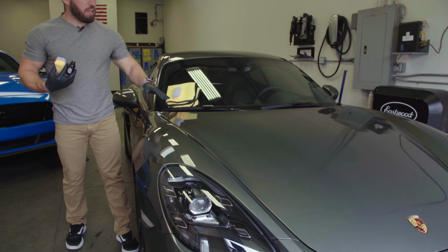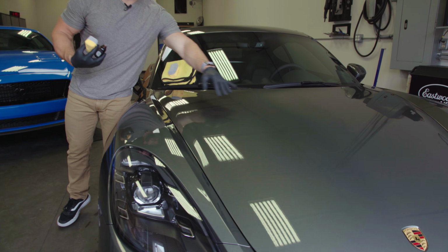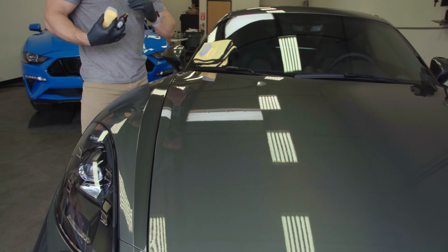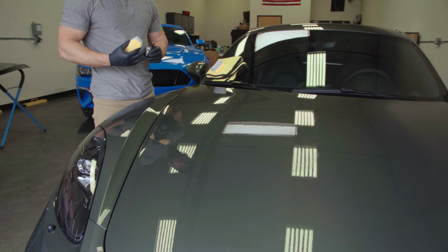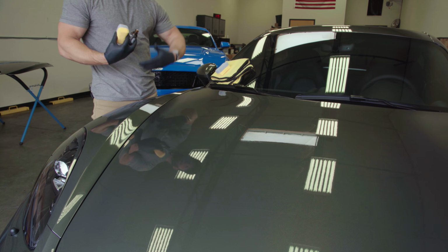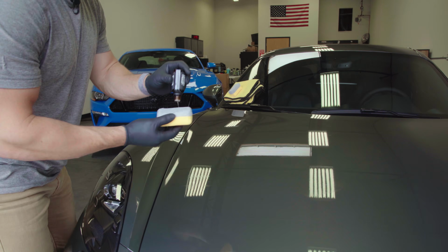And as you can see, after the application, you have a nice little rainbow. Now, this rainbow is what's known as flashing. So there's ingredients and solvents in the coating that will flash away and evaporate once applied. That actually helps you indicate when the coating is ready for wipe off. Now, it's flashing, rainbowing pretty good right now. Once that rainbow starts to fade or starts to be more of a haziness and the rainbow starts subsiding, that's a good indicator that it might be ready for us to start wiping off. So I'm going to finish this other half of the hood here.